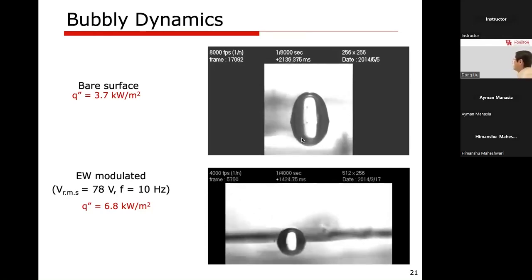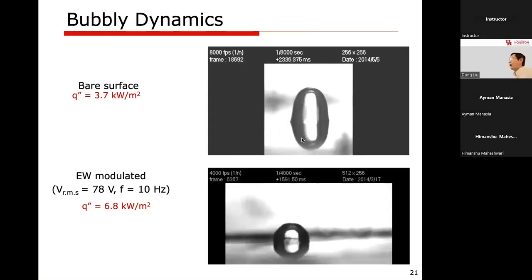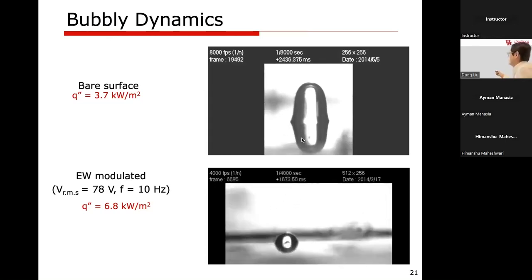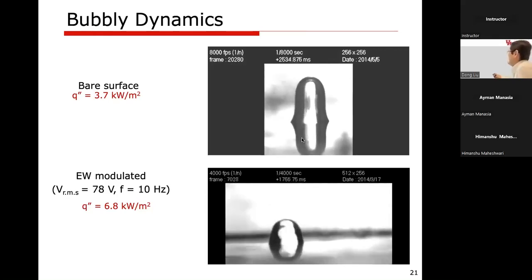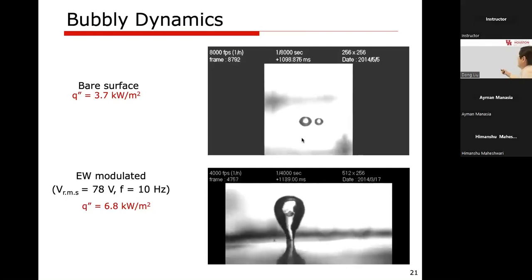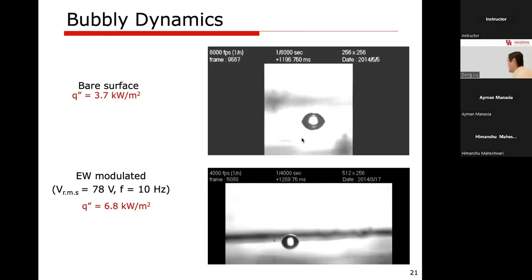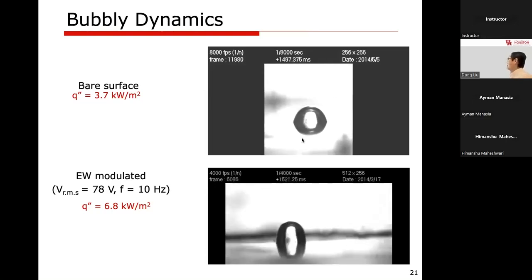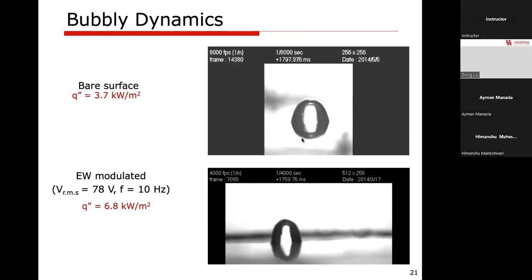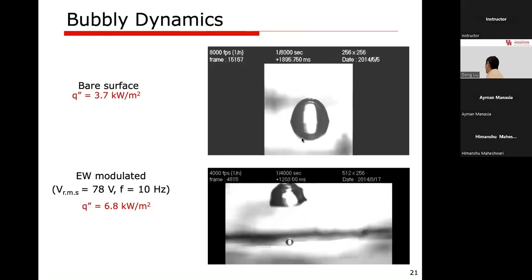But in general, you can see on the bare surface, the bubble will stay here for a very, very long time. And when it departs, it has a very big size. You can read the number in real time. And so here you can compare the numbers. So with electrowetting, we can increase the departure frequency by probably tenfold, and also the departure size becomes much smaller than what happens on the bare surface. You can see over the same time frame, this bubble still stays, but you have multiple bubbles already formed, grown, and departed.